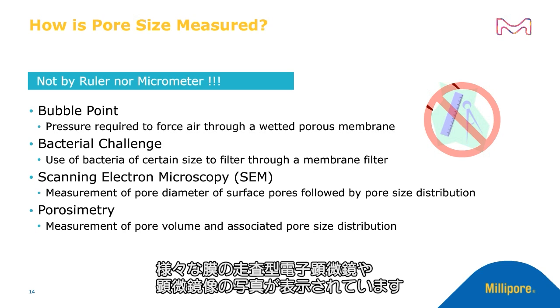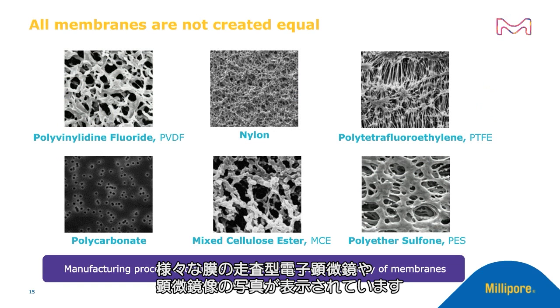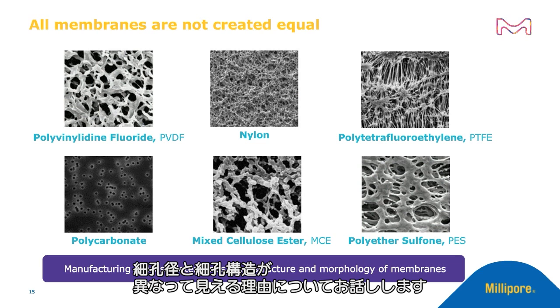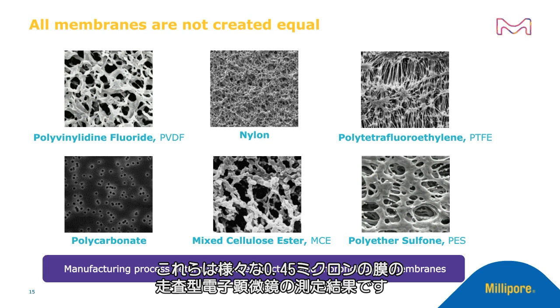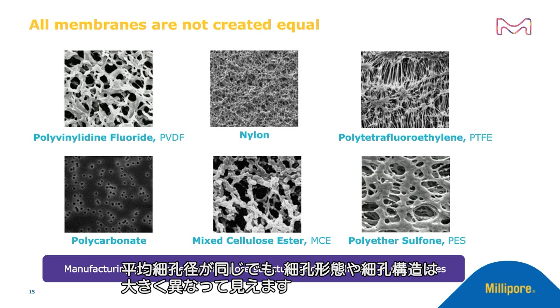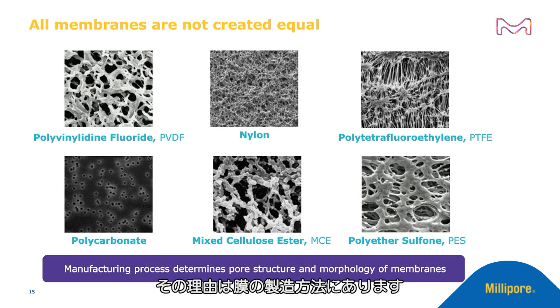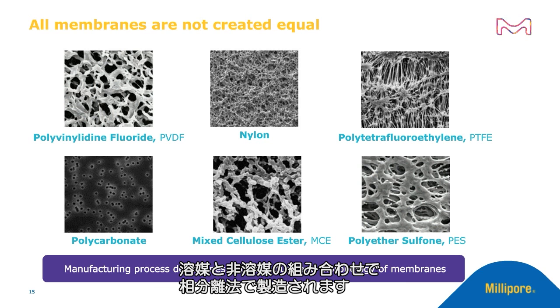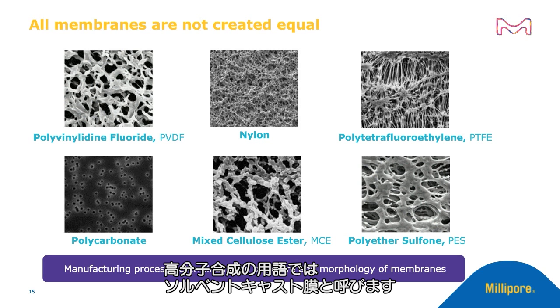Here are scanning electron micrograph pictures of various membranes. And let's talk about why the pore size and the pore structure look very different from one another. These are scanning electron micrograph images of various 0.45 micron membranes. As can be seen, even though these have the same average pore size, their pore morphology and pore structure look very different. And the reason for this difference is the way in which these membranes are manufactured. For instance, the PVDF, the PES, and nylon membranes are made by phase separation using a solvent and a non-solvent combination. Or in polymer synthesis terms, these are called solvent cast membranes.